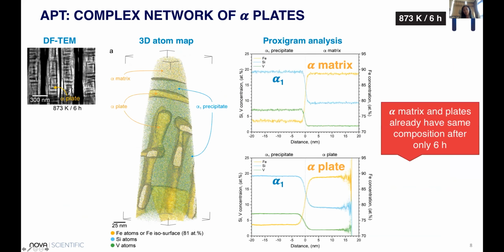Okay, now let's take a look at our atom probe data, this time of a sample aged for 6 hours only. In the 3D reconstruction, we can now clearly see how the alpha plates are interconnected, forming a 3D maze-like structure. The interfaces are visualized with an 81 atomic percent iron isosurface. The proxigram between the alpha-1 precipitate and alpha matrix, and between the alpha-1 precipitate and hierarchical alpha particles look identical. The alpha matrix and hierarchical particles have the same composition.